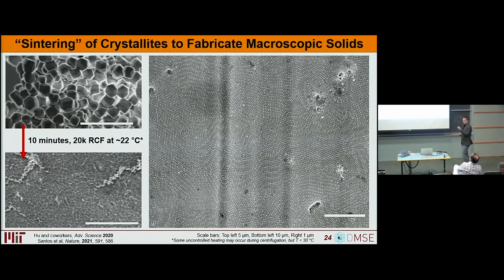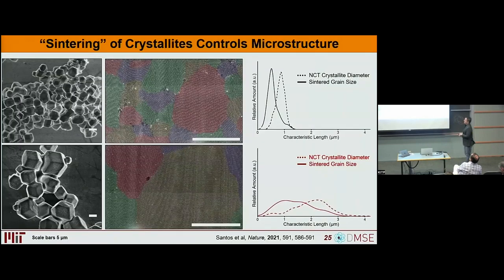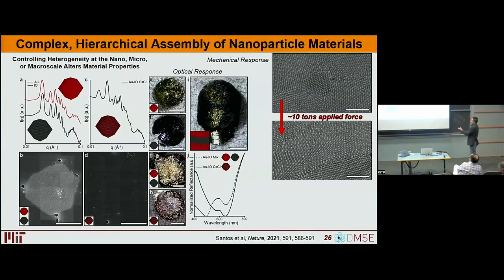So we can go from individual single crystallites that are typically on the micron scale size regime, and now we can make something that is actually large enough that we can think about it as a bulk macroscopic material. We can use this to tailor the microstructure. Small crystallites tend to give us small crystallite domains. Large crystallites give us large domains. We can think about controlling the heterogeneity by mixing and matching these different types of structures.